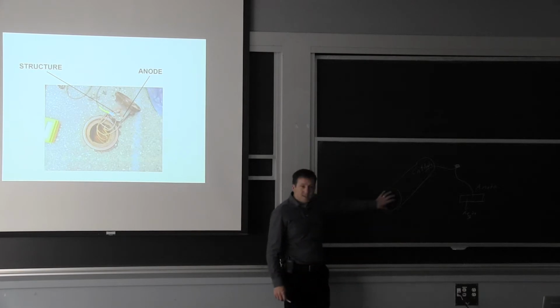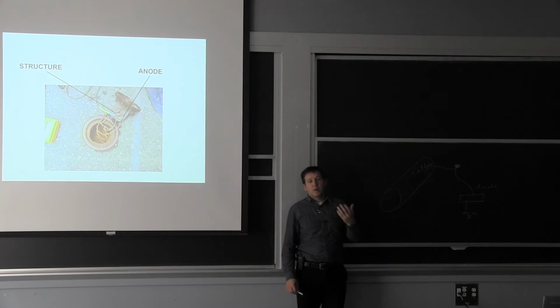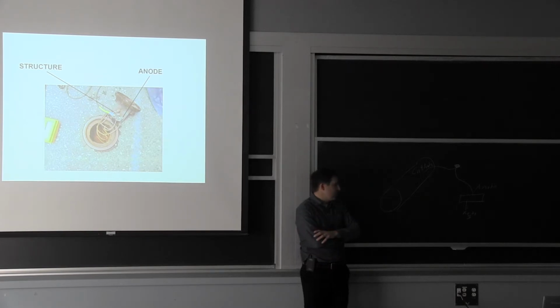If you try to do this in concrete, for example, it's a lot more of a problem because now we're talking about a pretty solid material. So all our ionic conductivity is really reduced. So you end up having to put it about a foot away or less than a foot away. So it becomes very difficult, especially if you're doing it after the fact.